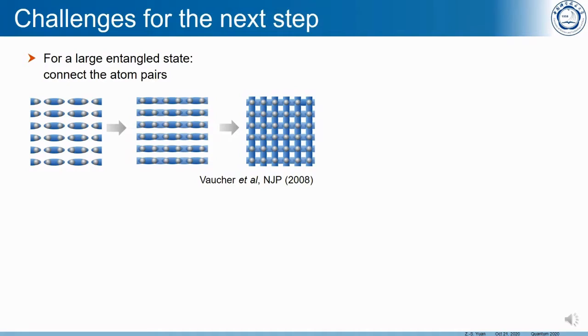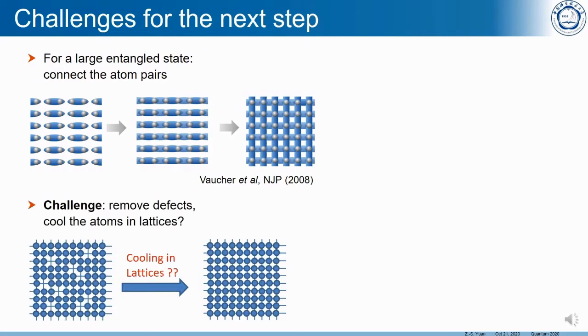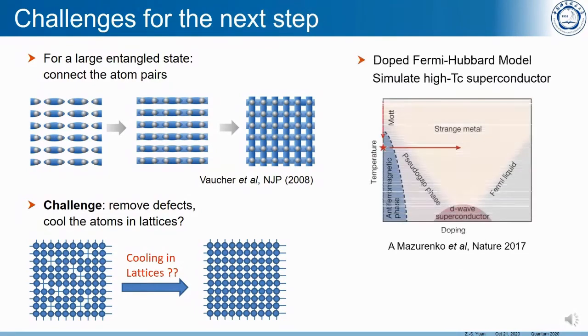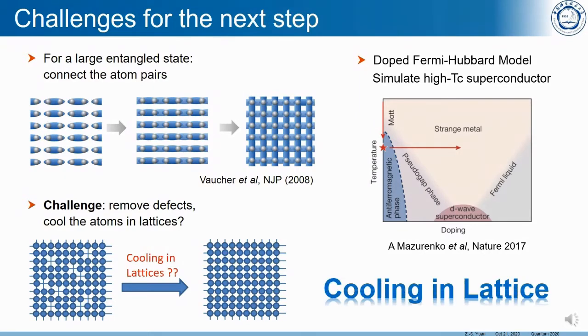Until now, one may ask, why not directly connect the atom pairs to create large entangled states? Actually, there is a challenge that the temperature of the lattice is still high. We still have some defects in the lattice. Therefore, we should cool the atoms more. On the other hand, for simulating high-Tc superconductors with the doped Fermi-Hubbard model, we need to cool the atoms more to reach the regime for observing d-wave superconductors. Therefore, the two applications have the same request of cooling atoms more in the lattice.